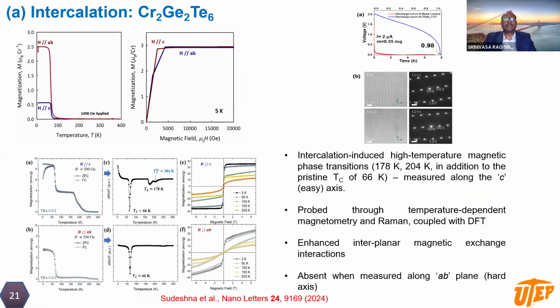And we expanded this work to another independent layered compound, chromium germanium telluride. We used the same intercalant, TBA+, which is known as a very strong electron donor. We conducted measurements in the pristine case, and it showed typical Curie behavior with a Curie temperature of about 66 Kelvin. As you can see, in the pristine case the Curie temperature is about 66 Kelvin. It is consistent with the reported value.